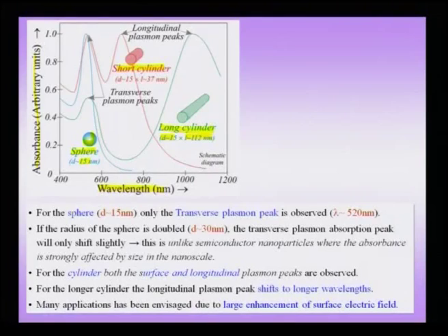Now, for a sphere of about 15 nanometer diameter, and here is that blue sphere which is 15 nanometer diameter, only the transverse plasmon peak is observed at lambda approximately 520 nanometer. So, if I look at this blue curve corresponding to my transverse plasmon absorbance, you see that it has a peak around 520 nanometer. There is only one peak, that is very, very important to note, and this is coming from transverse plasmon,